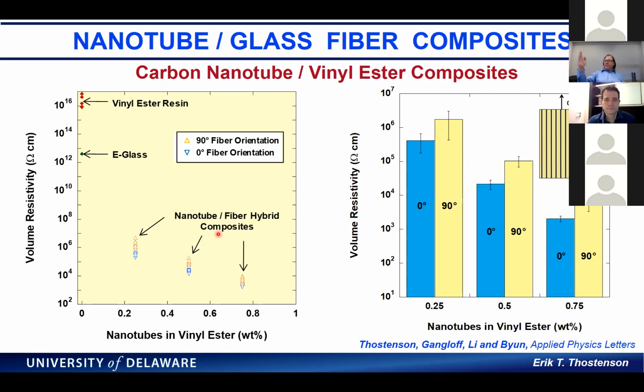The one thing that we did notice, which we weren't expecting, and nobody had reported it at the time that I had seen, was that the volume resistivity was a bit anisotropic. Chunyu Li, the third author, did some modeling, and along the fiber there is a lower resistivity, or higher electrical conductivity, because it's statistically more likely that the tubes are going to create spanning clusters. But in the transverse direction, the 90 degrees direction, the tubes have to go around the fibers, so it's a longer mean path. It has to fit through the gaps, right?